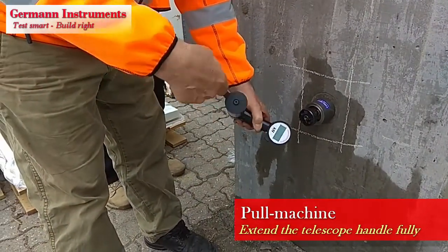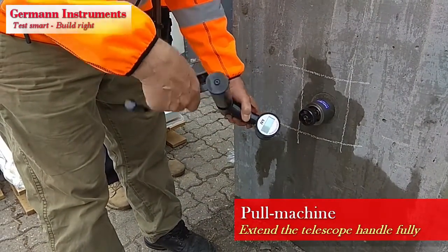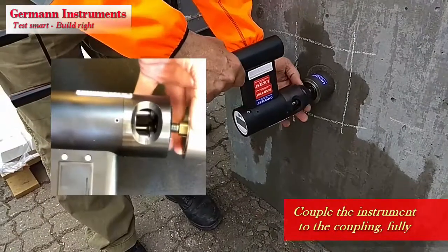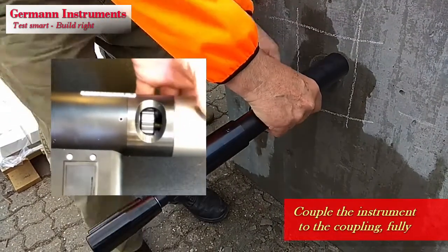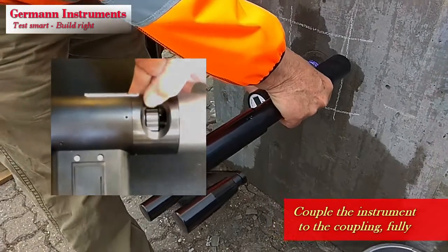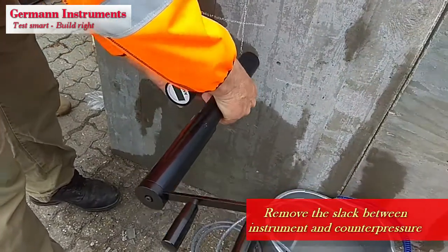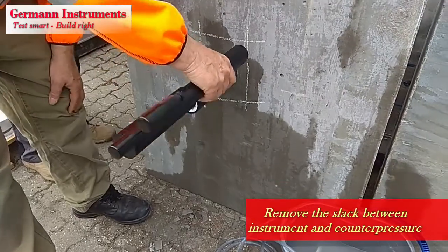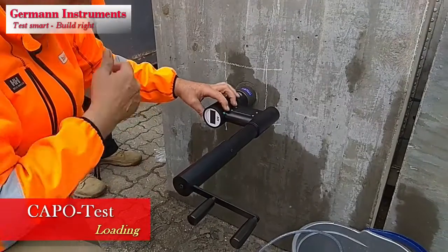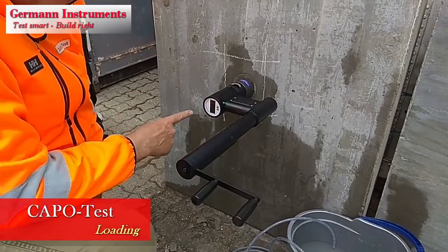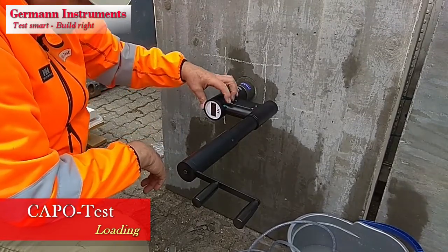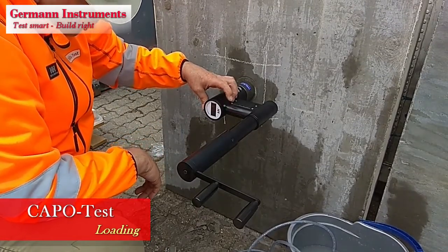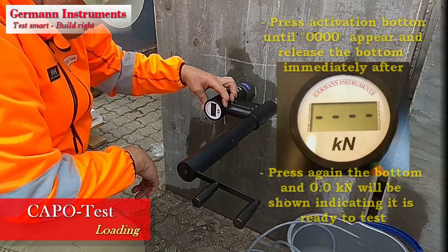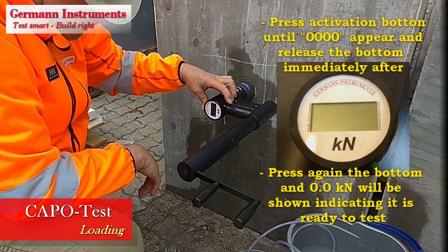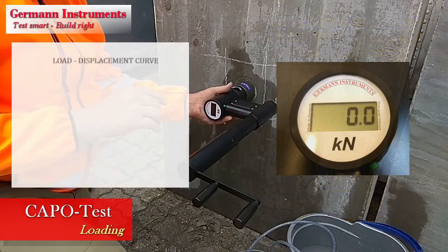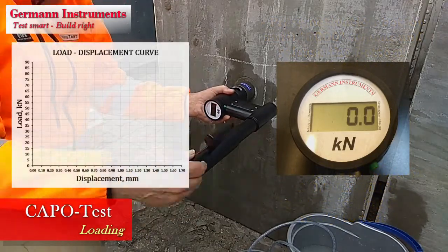Activate the hydraulic pull machine by extending fully the telescope handle. Couple the CAPO coupling to the pull machine. Make sure the coupling is fully engaged. Remove the slack between the pull machine front surface and the counterpressure by turning the instrument clockwise. Activate the green button on the instrument's gauge. Press it until 0000 turns up. Release it and activate it again, shortly. The gauge will now show 0.0 kN, indicating it is ready for testing.